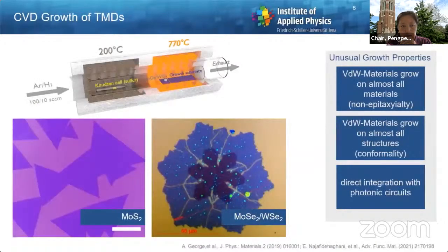So the approach we pursue is we use chemical vapor deposition, where you basically take vapors of chalcogenide, in this case sulfur, and of your transition metals, and then you bring them in contact with your growth substrate in the reactor under specific circumstances. And if you do everything right, you will observe growth of monolayer crystals on your substrates. As an example, here on the bottom left, these are monolayer crystals of molybdenum sulfide.